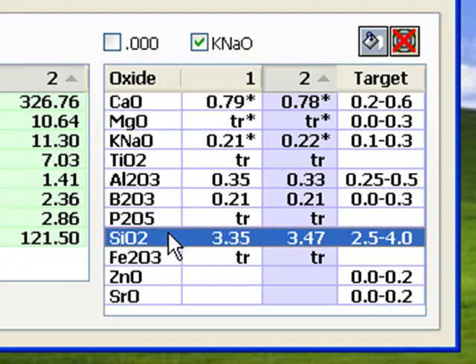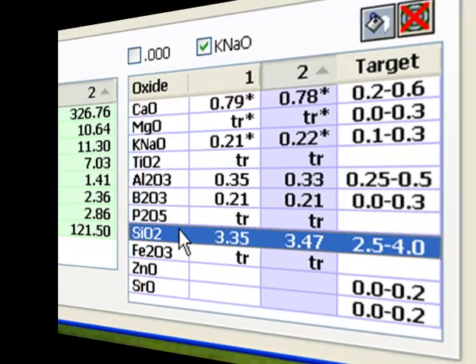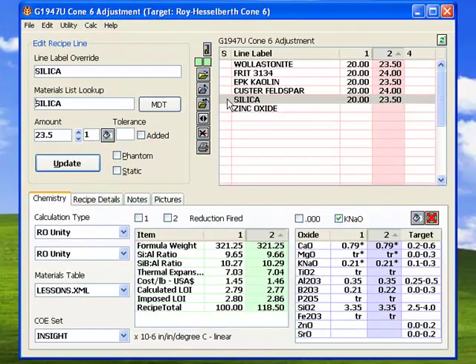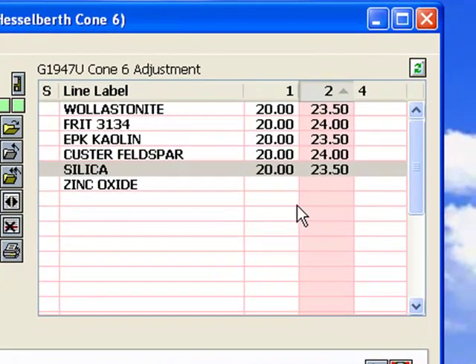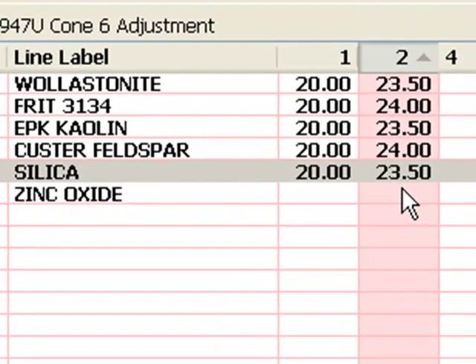Now you know why this frit is so popular — it has a balance of oxides similar to most glazes, so adding it to supply boron does not disrupt the chemistry too much. The Cone 6 recipe and our adjusted Cone 10 one now have the same chemistry. The recipe of the adjusted Cone 10 glaze has almost equal parts of the same five materials. That means chemically, the standard Digital Fire 1214M Cone 6 transparent recipe is just our standard 1947U Cone 10 transparent plus 0.2 molar parts of boron and no zinc.